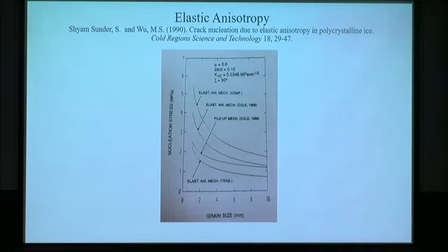However, our model shows a difference in prediction between compression, which is at the top, and tension, which is at the bottom. Now, why in our model could we predict a difference in nucleation stress between compression and tension? It's because we use the idea of friction. When the precursor is under uniaxial compression, for example, the precursor faces rub against each other. So the resolved shear stress acting on the precursor crack is reduced by the friction, and you need to apply more remote stress to overcome that friction. That is the basic reason for an increase in the nucleation stress for compression over that in tension. Cole's model, of course, did not use the idea of friction, so there is just one result.